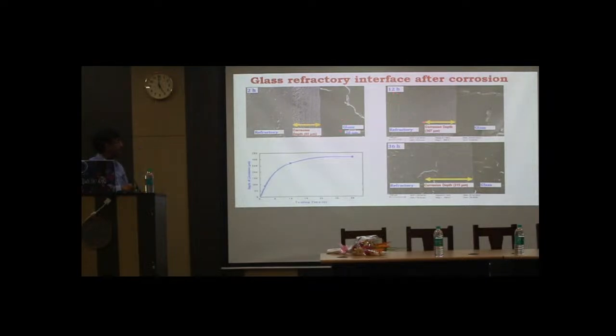And when we kept the sample for 12 hours, the depth is 267, and again at 36 hours the corrosion depth is 315. So from 0 to 2 to 12 hours, there is quite an increase in the corrosion rate. Initially, although it is not linear, with time it ceases, and that's why at 36 hours there is not too much increase in the corrosion depth. And we analyze these things. So it is not following a linear equation. In some cases, many authors find that it is a parabolic equation, but we find that in our case it is not even sub-parabolic.